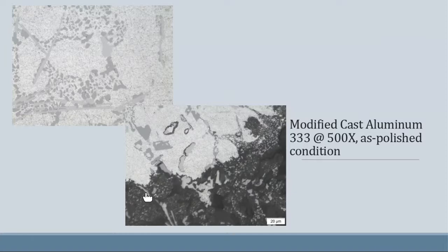The hydrogen is eating away at the aluminum alpha solid solution phase. So you're getting that preferential attack of the aluminum matrix. Looking at this, this is your aluminum matrix, all the white. If you're transitioning and you look at this, it's attacking anywhere there is aluminum. You can come through all of this region that used to be aluminum, and you can see where all of the intermetallics are still intact.